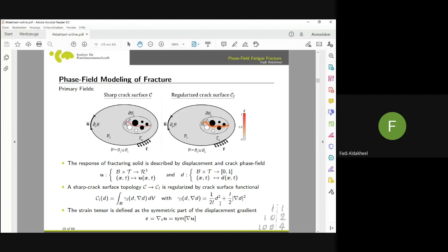The phase field D by itself is scalar, right? So it's a field, but you include it coupled with the gradient of D, so you include information about anisotropy in the gradient part. That is one possibility. If you want more than transverse isotropy, like orthotropic or cubic symmetry and so on, then it's not only one field or one variable that needs to be added. Then you need to talk not about second order, but fourth order, right? So you have to increase the difficulty of the analysis of the response. This is a possibility, and I will show you something soon about that.